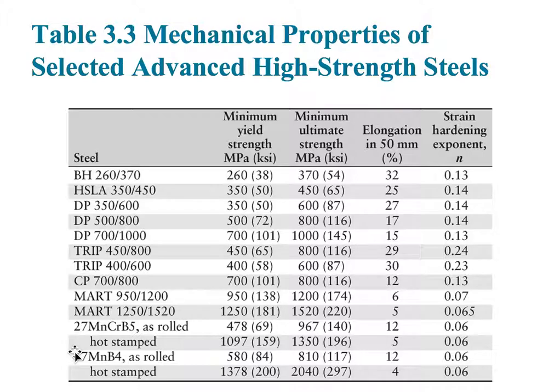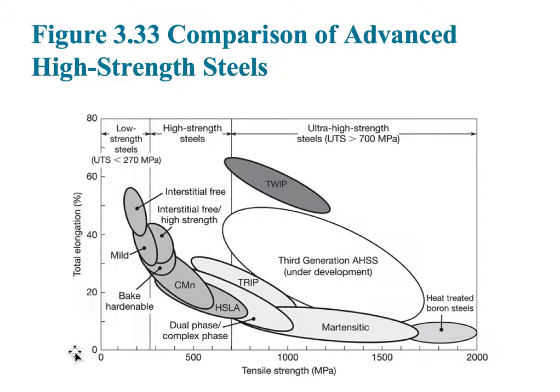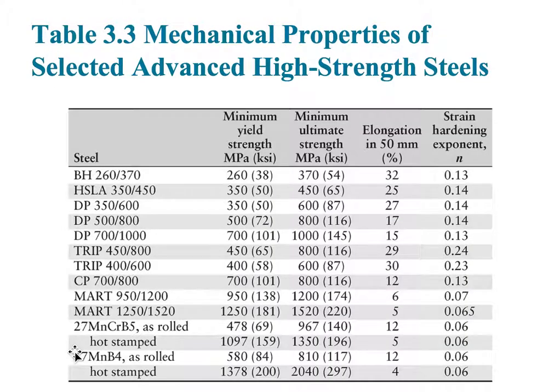So here are some tables of mechanical properties of selected high strength steels. You can see that as rolled, hot stamped, etc., its tensile strength goes up, your yield strength goes up, but it doesn't mean that its fatigue resistance goes up. The other thing is that its strain hardening exponent also changes. This will tell you how easy or how difficult it is to make a component from that material.